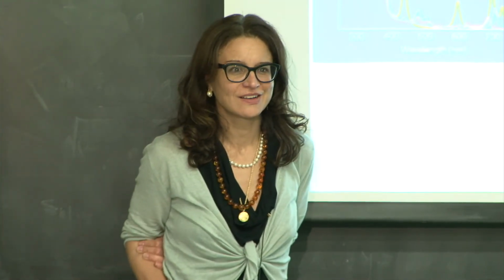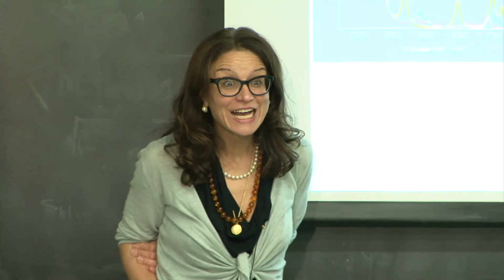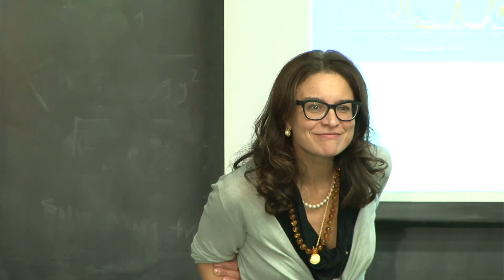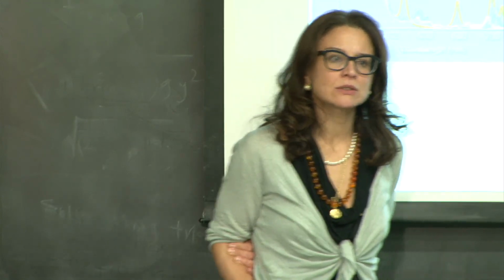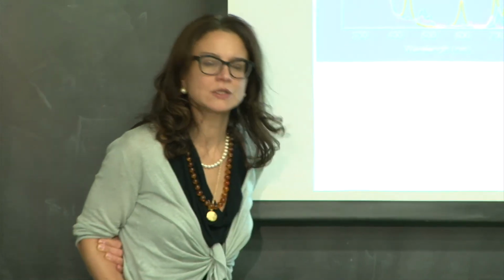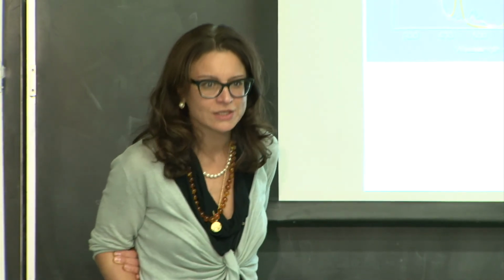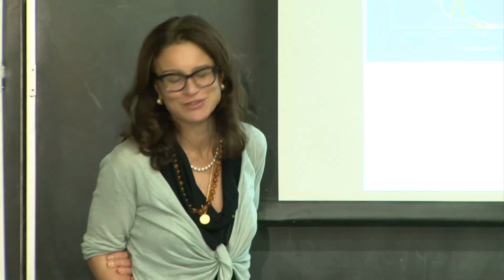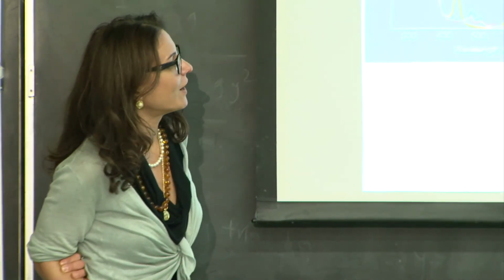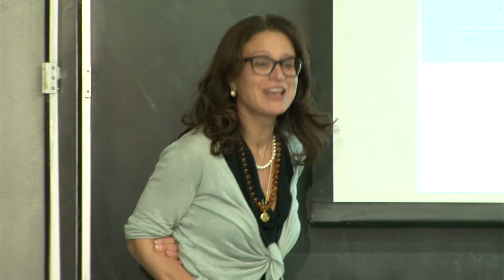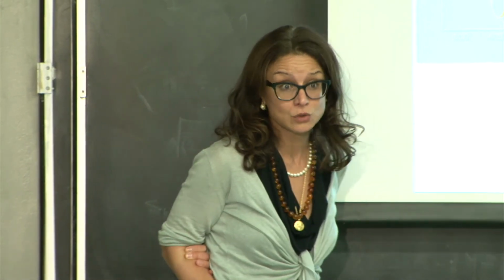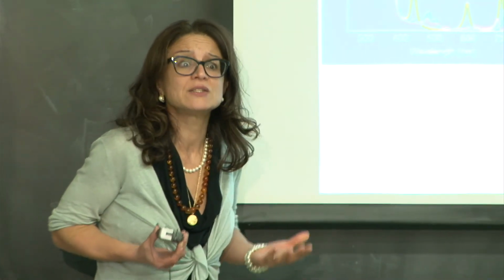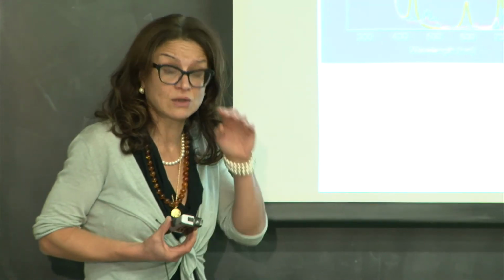I have a question about the stability of material properties, for example the battery application. How many charge cycles do we see until the battery efficiency starts to drop? About 20,000, 25,000. It's surprisingly decent. And look, I'm very conservative and slow when it comes to publishing, ridiculously slow. Students are not always happy, I have to be honest, but we ran more than 20,000. And what is surprising, it's stable even under light conditions.